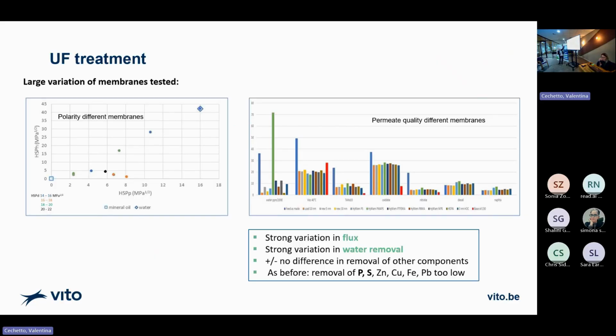You see actually the polarity of the different membranes we used here. I plotted it using the Hansen solubility parameters. I'm a big fan. So you see here the polar Hansen parameter and hydrogen bonding, and it goes from the native membranes, which are water-like polarity, down to no polarity at all, which is here in the 0 point, the oil itself.